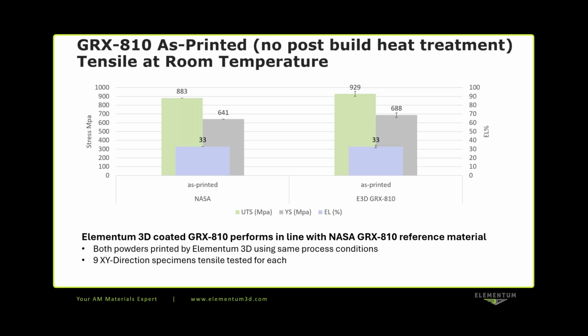So as printed with no post-build heat treatment, we wanted to just look at tensile properties at room temperature as a starting point. Even though this is not the primary use case of the material, it's still a good way for us to compare: is our commercial scaled material doing what it should compared to the reference material from NASA. And we found that our coated GRX 810 performs in line with NASA's GRX 810 reference material. Both powders are printed by Elementum 3D on our EOS M290 using the same process conditions. And this data here is a limited data set for initial comparisons, looking at just 9 XY direction printed specimens for each test material.